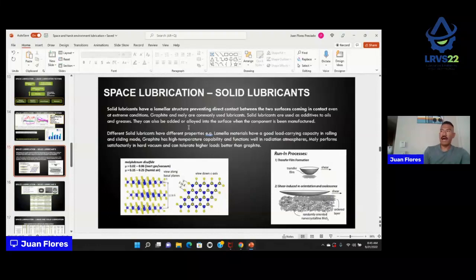And then I'm pretty sure that most of you are familiar with solid lubricants. Solid lubricants are normally based on molybdenum sulfide, graphite, or PTFE. And the beauty of these materials is they have very low shear strength. The molecular bond is usually covalent, so it's very strong. But between the molecules, it's just a van der Waals force. Therefore, you can easily shear this material, and because of this low shear, they have a very lubricious type of surface. So that's the main difference with the liquid